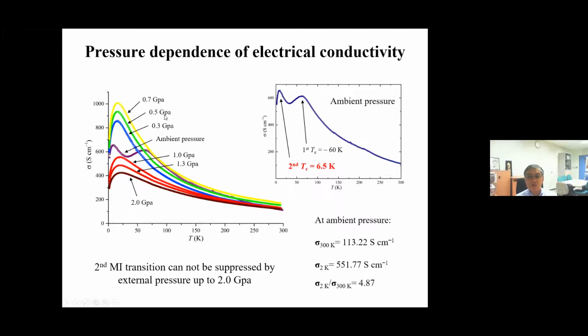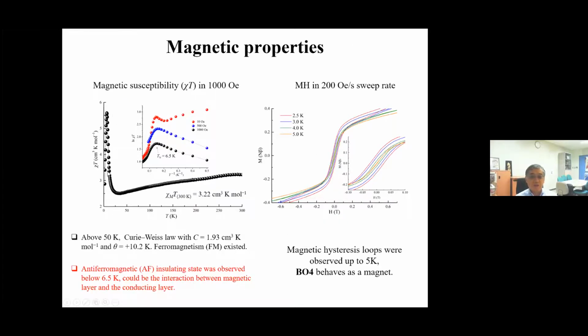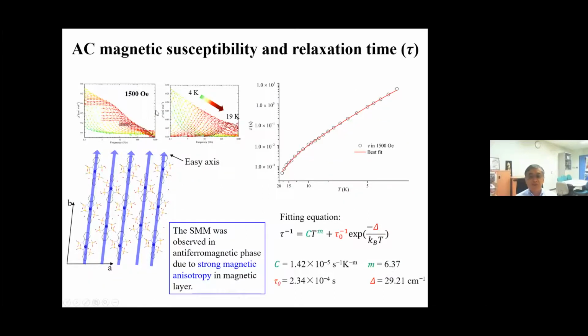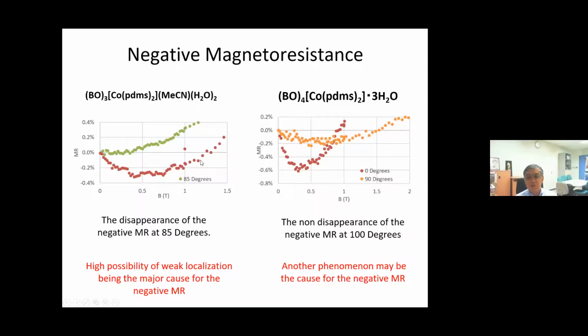What happened? We measure magnetic susceptibility. So antiferromagnetic interaction is observed. So then the conduction electron and the local magnet interact with the antiferromagnetic interaction. However, below the antiferromagnetic interaction temperature, we observe the SMM states because the single magnet survives below the antiferromagnetic temperature. Then frequency dependence is observed below 6.5 Kelvin. So because the single magnet survives, the single magnet and the conduction electrons interact, a deeper interaction. And also negative magnetoresistance is observed due to the conduction electron and localized single magnet.